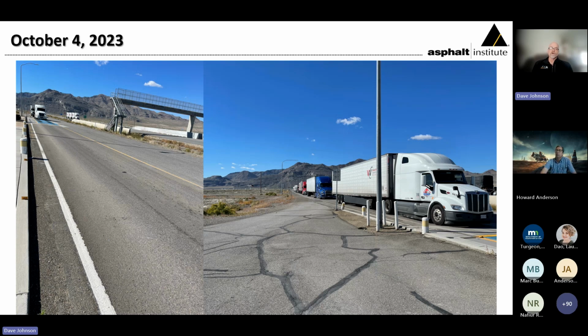All that cracking you see in the foreground, that is not this material. The material is only on the scale area. And the thing I want to point out, especially in this picture on the right, is notice that extremely long queue of trucks. Quite frankly, the trucks were queued all the way back to Interstate 80. They could not put any more trucks in this queue than what we see there. And this is not abnormal conditions for this site. So recognize that you have a significant number of trucks. They are going to be at a standstill for much of their time on this material. When they're not standing still, they're moving at very slow speeds.